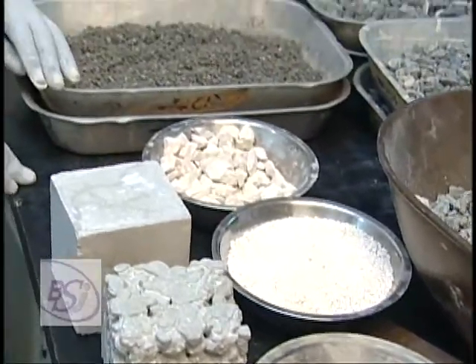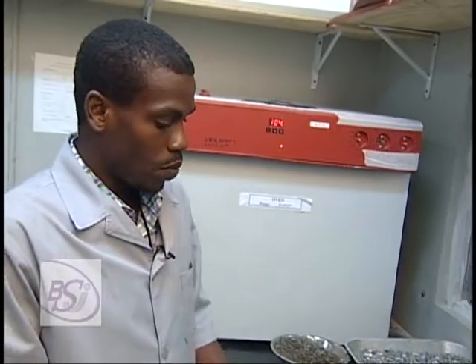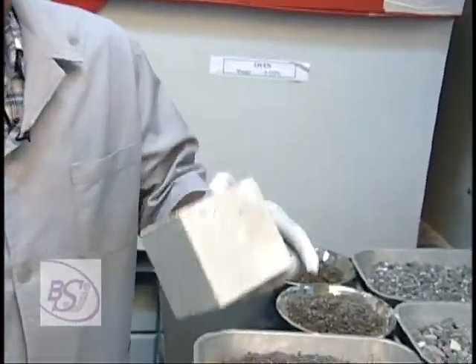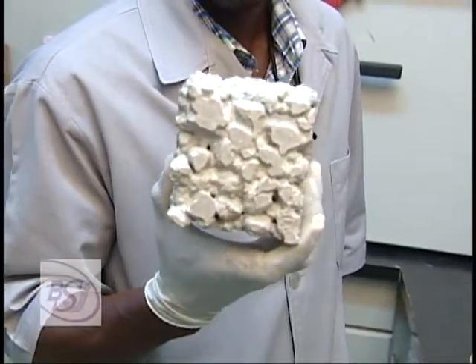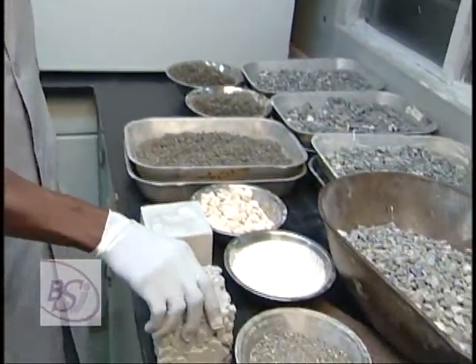What we do with our testing, especially for sieve analysis, we test for proper grading of the sample. With this proper grading, you perform a proper blending of coarse and fine together to give you a proper, dense concrete mix. If this is not performed, the result could be improper grading of aggregates, which could result in the slab leaking and porous concrete at a weaker strength. We will go to the quarries, collect the sample, test and give feedback on the results.